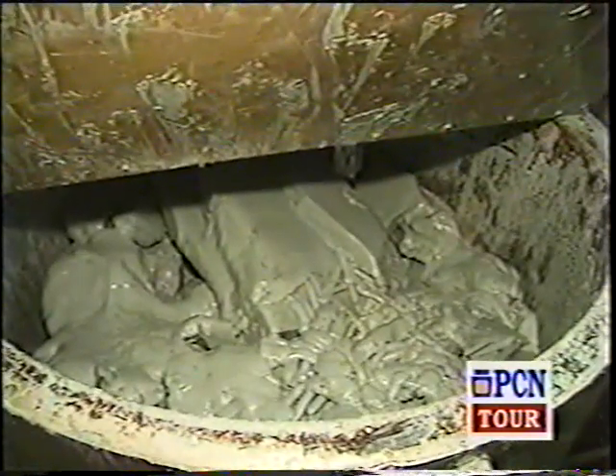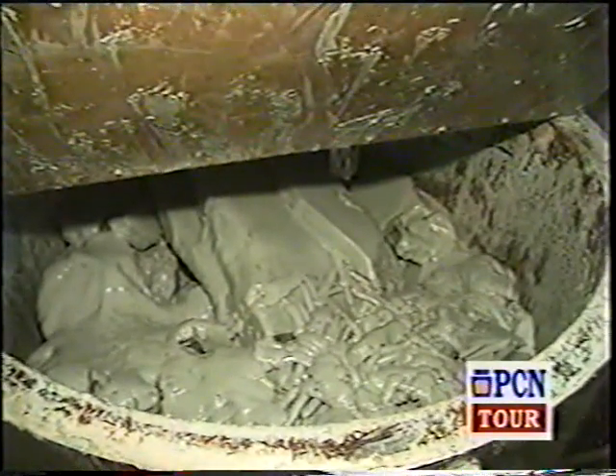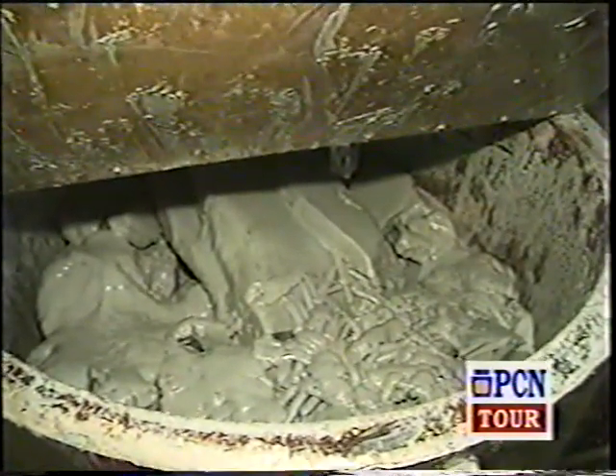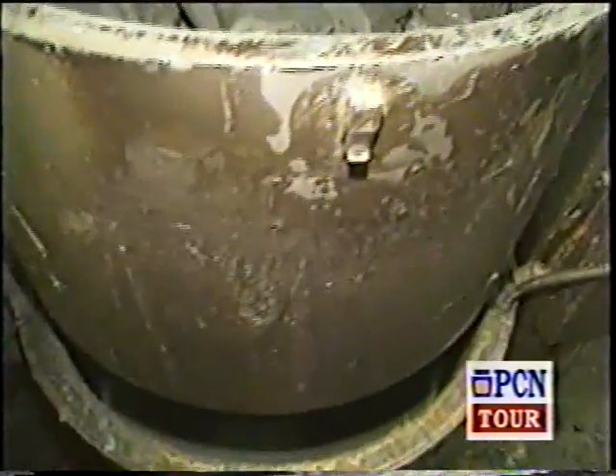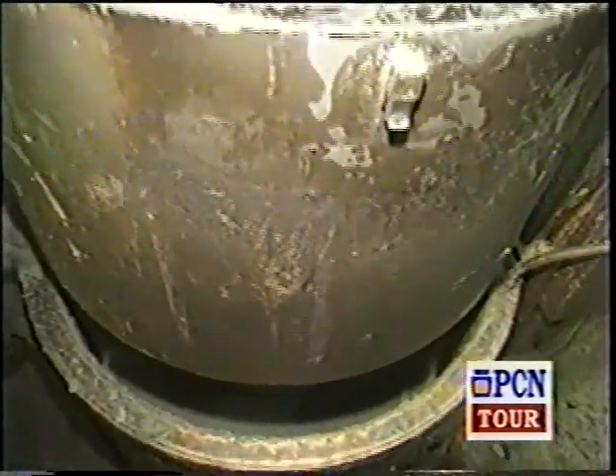Our process begins by taking the raw wax which we purchased and melting it in a melter at about 180 degrees. It drops into our conditioning tank where it's processed and maintained at about 150 degrees. From there, through a hydraulic pump, the wax is pumped to all of our injection stations, which we will now walk into that room and see.